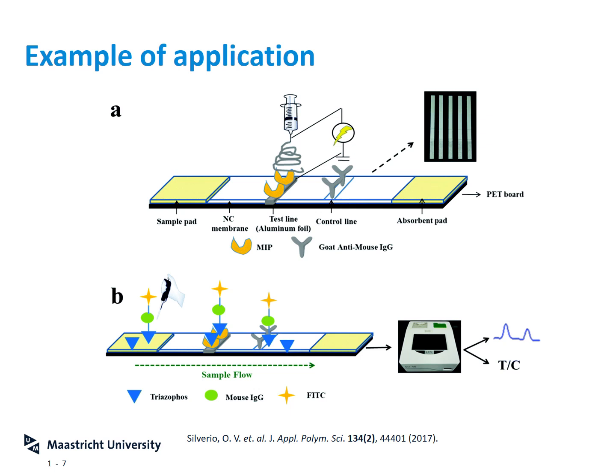However, when there is pesticide present, the pesticide will also be transported to the test line and will bind to the MIP with a much higher affinity than the pesticide with the mouse IgG and FITC coupled to it. The reason for this is that the MIP has a higher affinity for the pesticide without the label on it, and will therefore preferentially bind to the bare pesticide present in the sample.